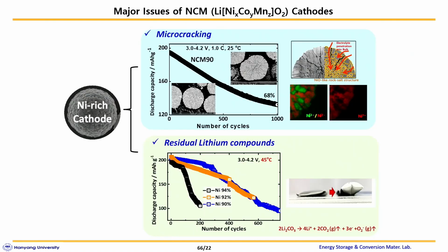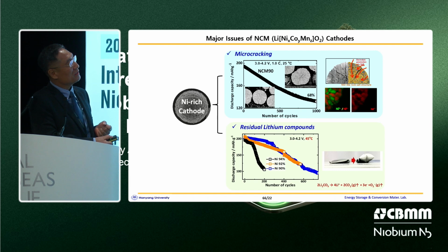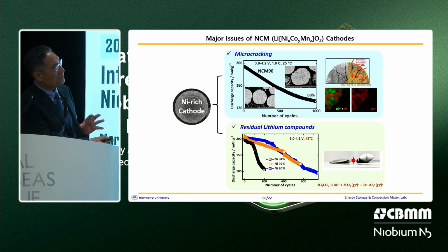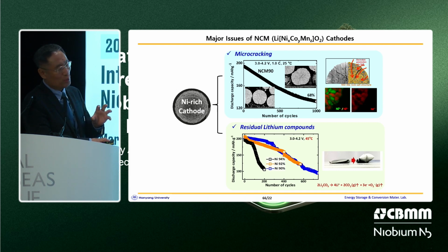And there are two intrinsic properties causing capacity fading of nickel-rich materials. One is microcracking, the other is the residual lithium compound issue. As I explained before, microcracking continuously leads to capacity fading by increasingly forming the rock salt impurity phase in the particle interiors. And the other issue is the residual lithium compound that easily decomposes and leads to cell swelling, which results in capacity fading.